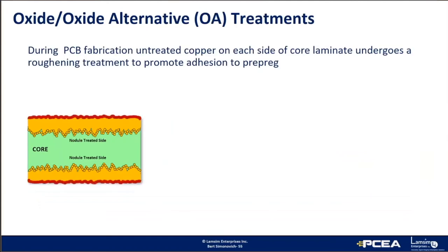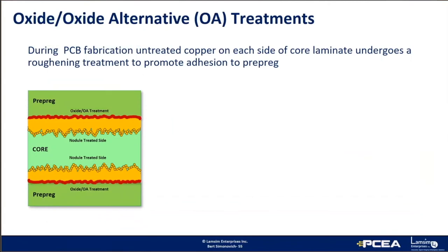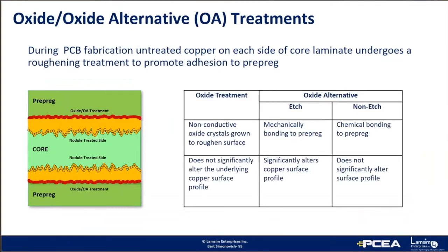During PCB fabrication, untreated copper on each side of the core laminate undergoes a roughening treatment to promote adhesion to the prepreg. There are two types of treatments, oxide and oxide alternative. In the case of oxide treatment, oxide crystals are grown to roughen the surface. It's non-conductive and does not significantly alter the underlying copper surface profile. On the other hand, there are two types of oxide alternative treatments. The first is an etching process, where the surface profile is etched to provide a mechanical bond to the prepreg. Non-etched oxide alternative treatment is a chemical bonding process and does not significantly alter the underlying copper surface profile.